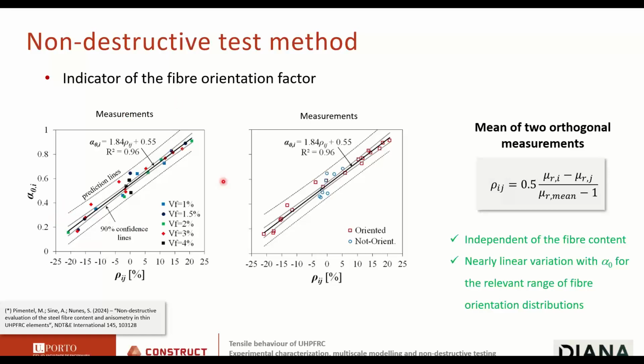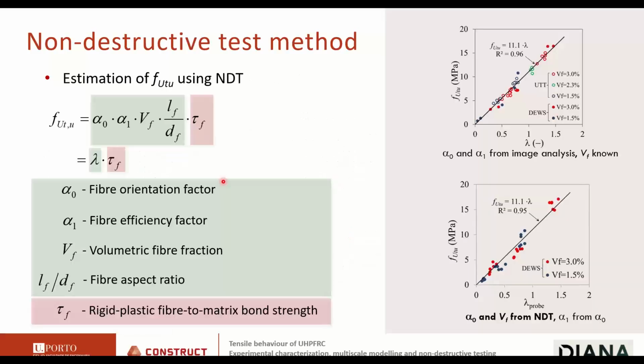So two linear relations, two orthogonal measurements, and we can get the fiber content and the fiber orientation factor at the point where we are measuring. And then we can use this data from NDT to predict the tensile strength, and we did it. I've shown you this graph before, where we have our fiber structure parameter determined using time-consuming, expensive image analysis. And here we have the same results, but using the NDT data. You see that the results are fairly close. So we don't lose a lot of information by using NDT compared to doing the time-consuming image analysis.